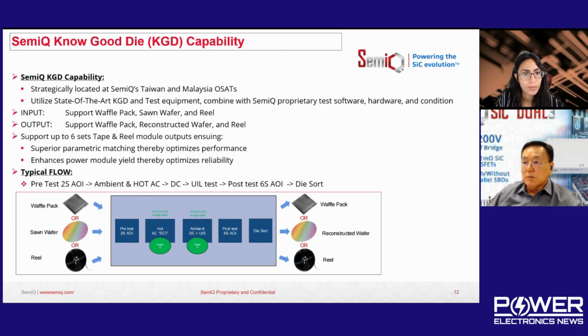And the third one we are developing is called SemiQ KGD. It is a different level of KGD, a single die. After slicing, the single die is tested in optical inspection, then at room temperature and high temperature, AC switching testing, DC parameter extraction, and then each die also has UIL testing, so it's avalanche breakdown testing. Then post six-axis AOI, and then die sorting into the wafer pack or reconstruction M by M array or tape and reel. So this is a very high-end, true KGD process.